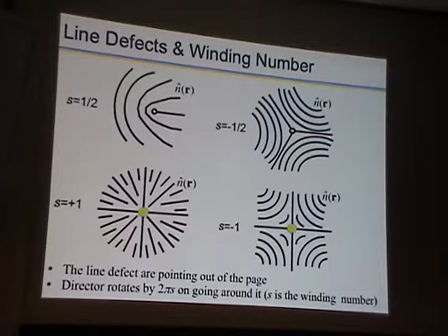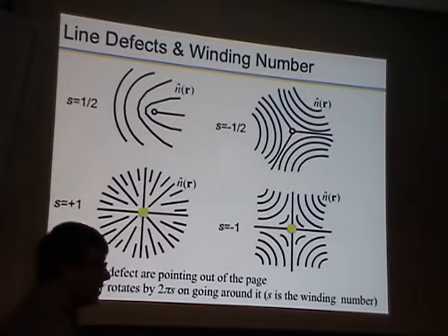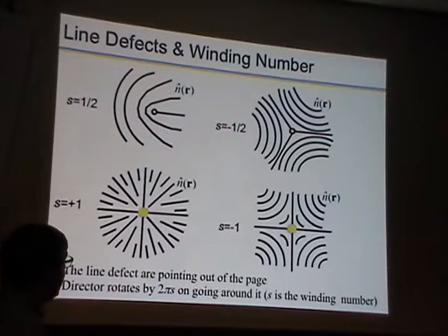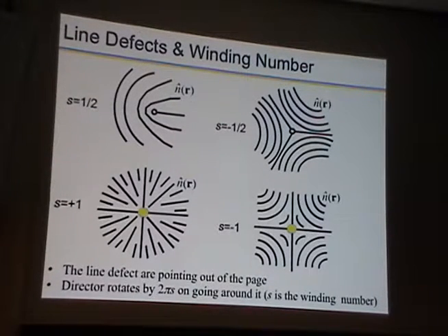Now, Jonathan in his talk already introduced to us topological defects, the 2-dimensional topological defects in particular, so-called disclinations or defect lines. In here, I again show you examples of such defect lines, right? So the 2-dimensional defect lines that we have in here are perpendicular to the screen. Those are the lines on which you cannot define orientation of liquid crystal molecules locally, right? And around the defect lines, we can characterize the local average orientation of those molecules by those director field lines that you already know a lot about. And so we can have defect lines with different strengths or different winding number. The ones shown here have half integer strengths of winding number here and integer strengths winding numbers.